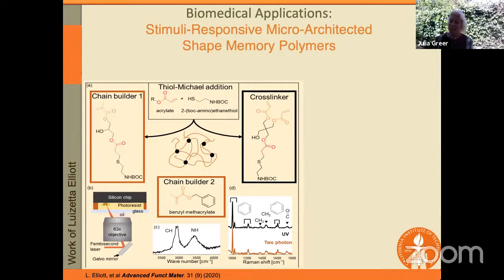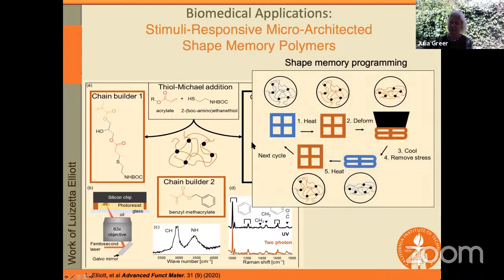There are a few more biomedical applications. What I'm showing you here is a so-called shape memory polymer. So there are two different chain builders and a cross-linker. And the idea is that we can take a certain shape and then we can heat it up. And as we're heating it up, we would deform it into a configuration that we want. And then when we cool it down under stress and then remove the stress, it stays in this shape.